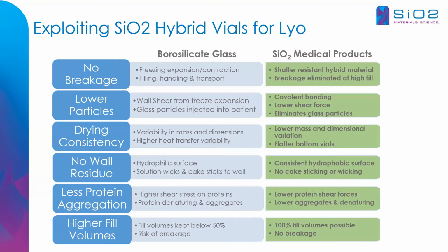And then another important one, particularly with multi-dose vials, which have been predominantly used now for COVID-19, is the ability to lyophilize larger volumes in the container. We have done a breakage study showing virtually no breakage in the SiO2 containers at 100% fill volume.